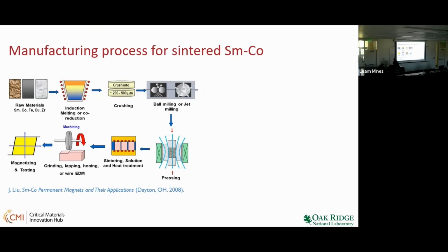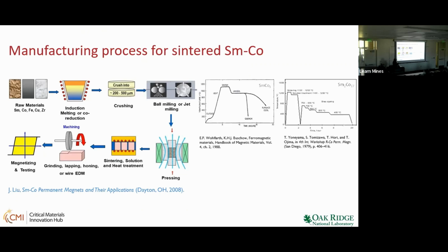One is 1:5, samarium 1, cobalt 5, or 2:17. So you will see there are two methods. What you are doing is, again, you are starting from the raw material, and instead of only cobalt, you may also add iron, copper, zirconium, and you are doing the induction melting. It's powder metallurgy, so you do the induction melting, then crushing, and ball milling into small powders. Then finally, you have again the temperature conditions we talked about, for sintered magnets. You go through this high temperature and slow cooling and two-step reaction, annealing and quenching and all.